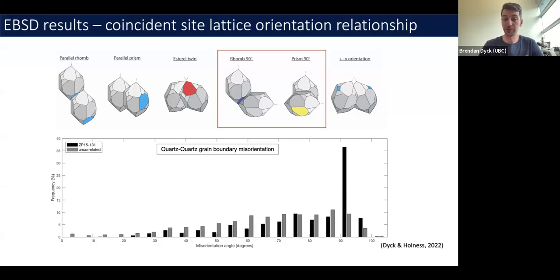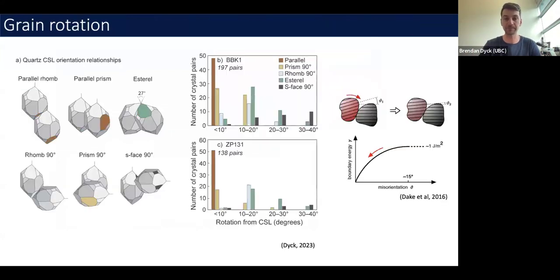If we collect cathode luminescent images, we can identify through the tree ring or oscillatory growth patterns of these quartz grains where we have two grains that came together and now they're parallel, versus grains that might have grown into a more irregular, clustered-like shape. And when we take that sort of approach, we get a bit more information.